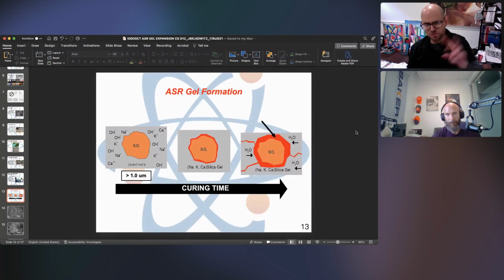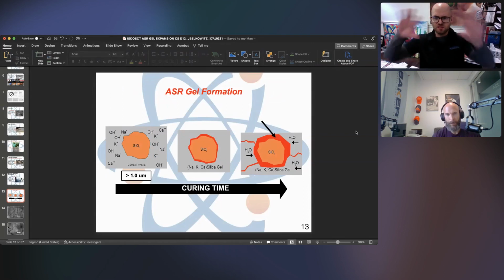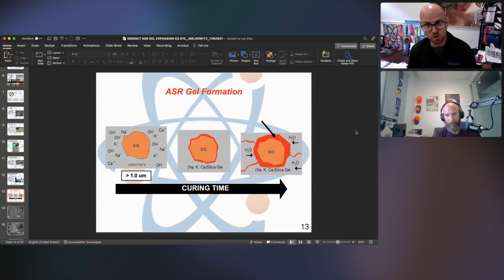What we have is many things that we can't get past. Let's just break it down to two things. We have a cementitious matrix, that gray stuff that has alkalis, other types of salts in it, and moisture and pores. Then we have our aggregate, which in certain areas can be a tetrahedral or reactive form with these salts. Over time, this silica and these alkalis plus moisture combine. You see here, this center picture shows the rock in the middle of the paste, the gray stuff.